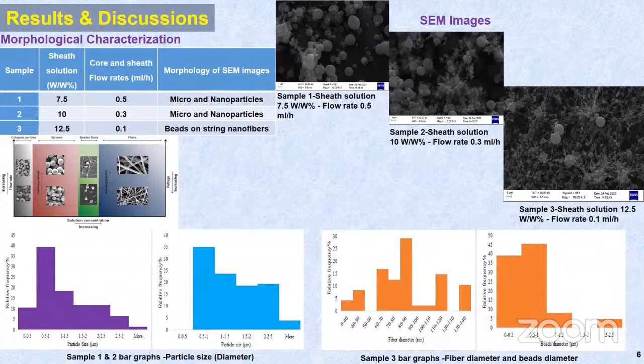Under results and discussions, morphological characterization could be summarized in the following table, parallel to the scanning electron microscopic images, which depict what has happened with the increase of sheath solution concentration from 7.5 to 12.5, while the core and sheath flow rates dropped from 0.5 to 0.1, resulting in a gradual change in morphology from more profound micro and nanoparticles to beads on string nanofibers, which in turn proves the transition from coaxial electrospray to coaxial electrospin. The bar graph in general shows the ranges of particle sizes of the first two samples and then the fiber diameter and bead sizes of the third sample.